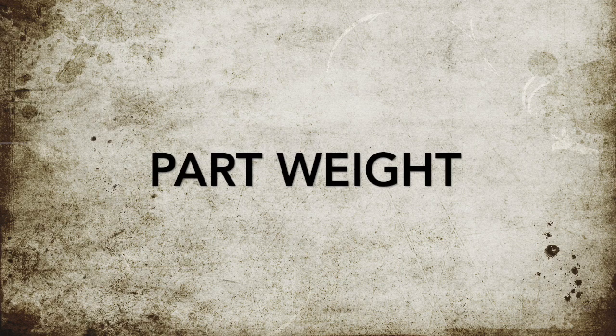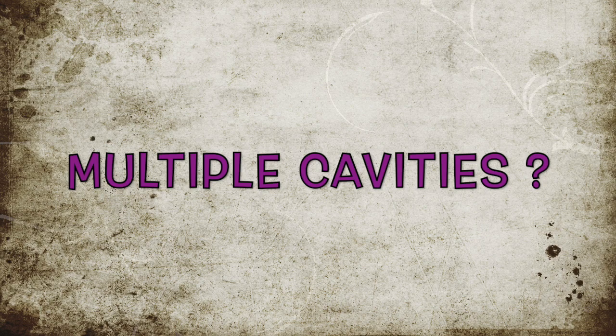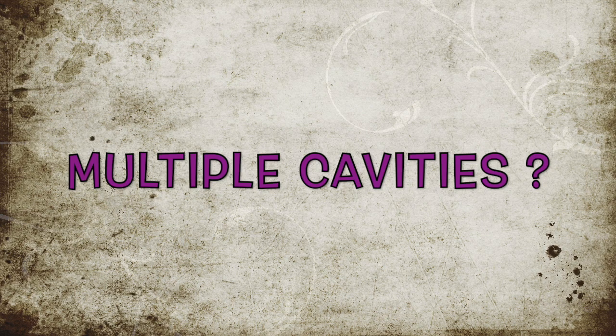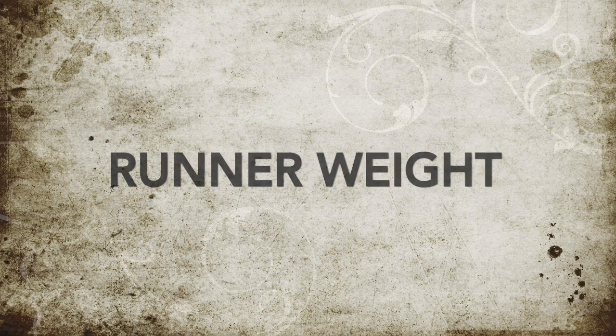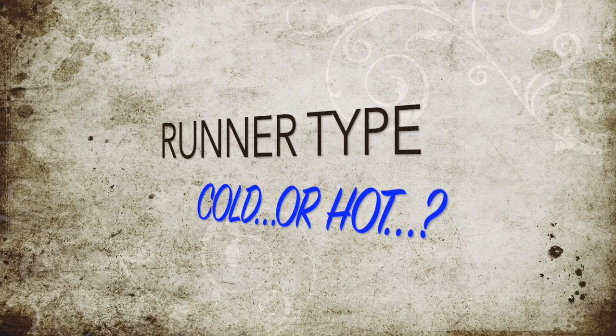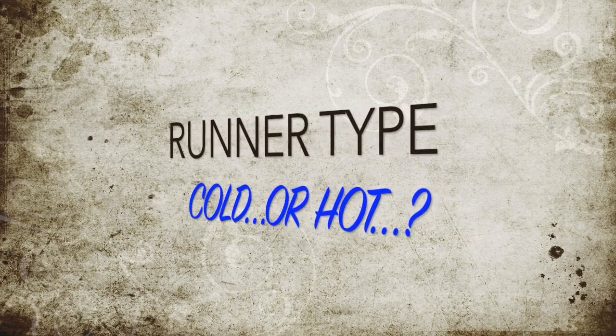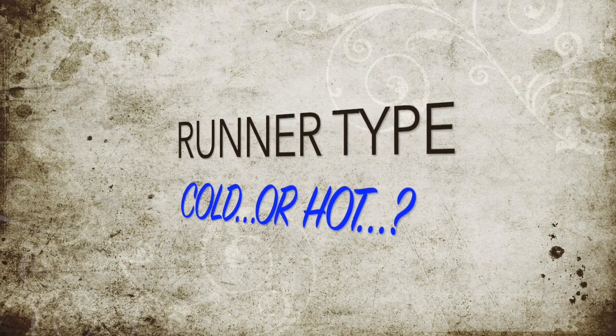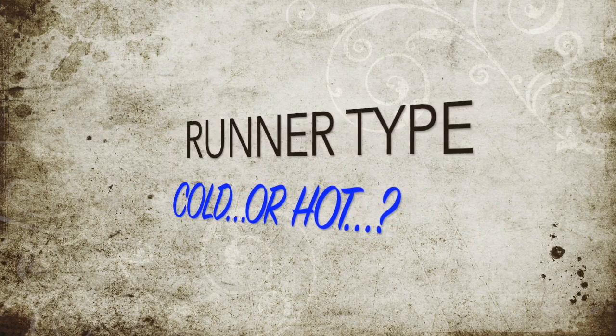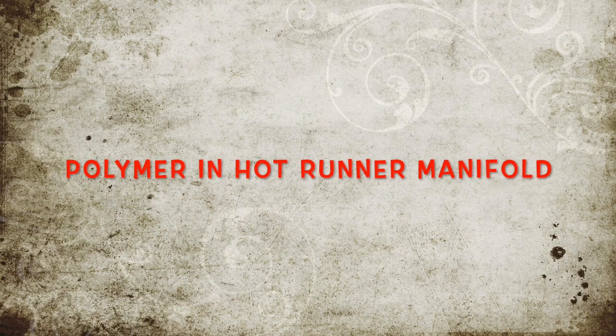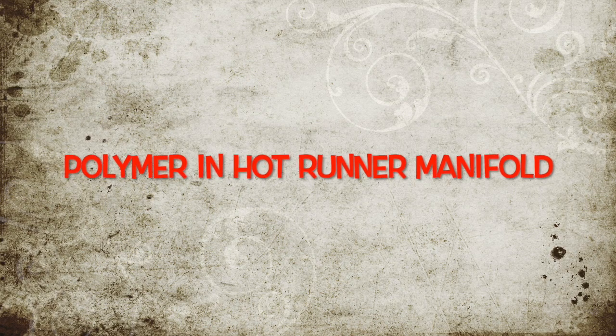Listen further. Part weight. This is the weight of the individual part being molded. If there are multiple cavities, part's weight is to be multiplied by the number of cavities. To this, add the weight of the runner. If this is a cold runner, just add the weight of the runner and sprue. If this is a hot runner, or a partial hot runner, add the weight of the cold portion of the partial hot runner to the weight of the polymer, which is always there in the hot runner manifold. Having done this addition, now we have the overall shot weight.